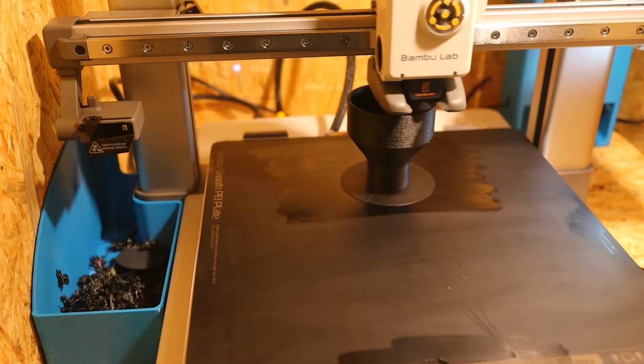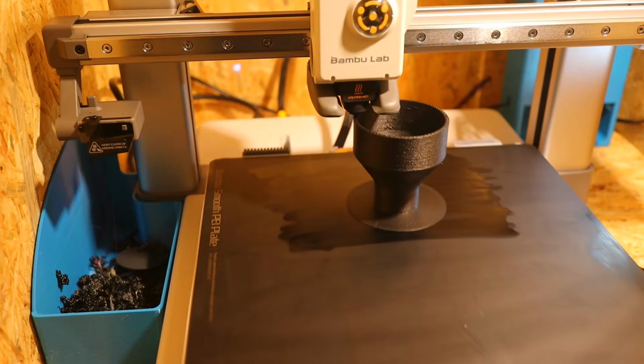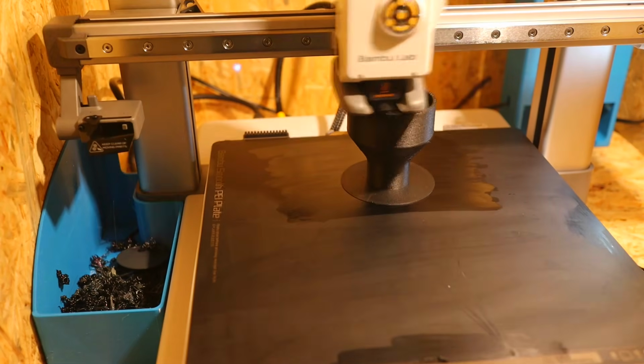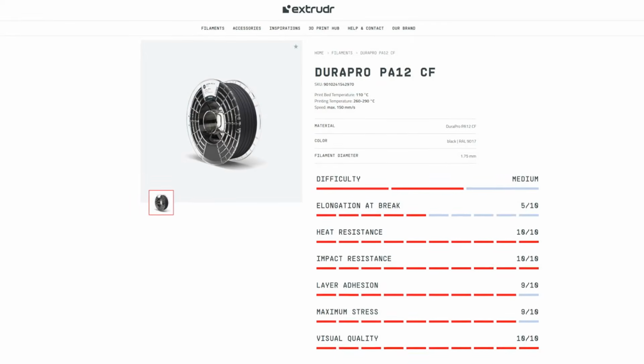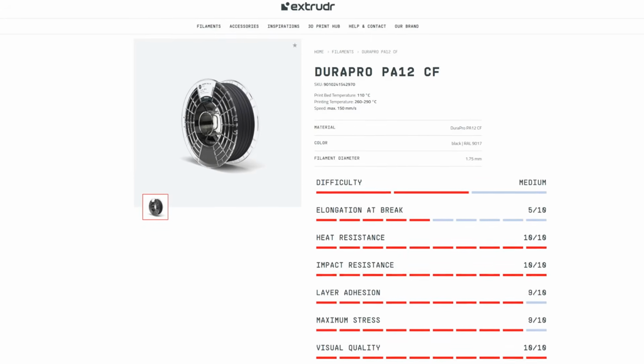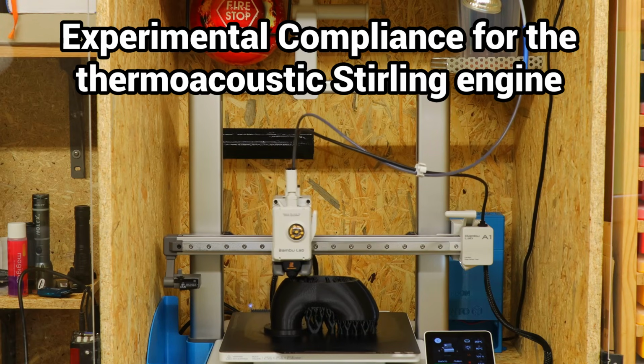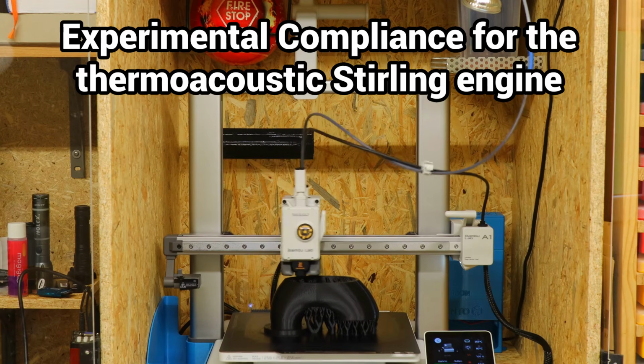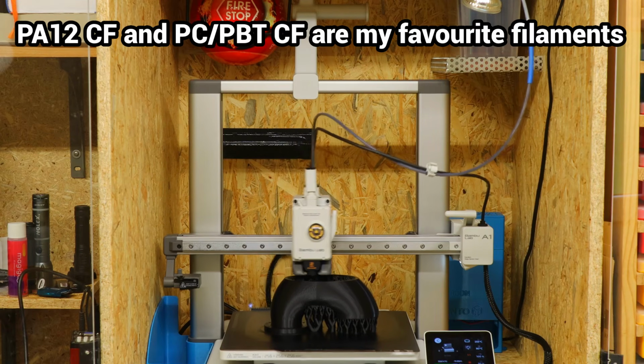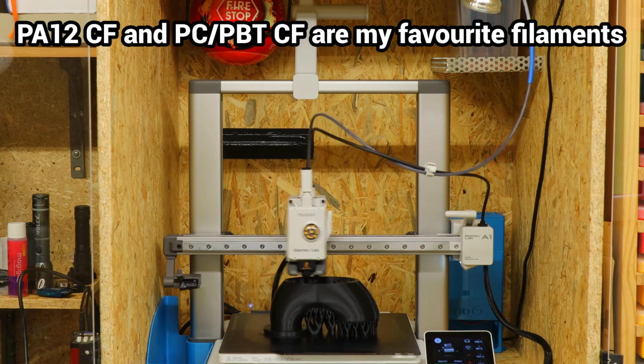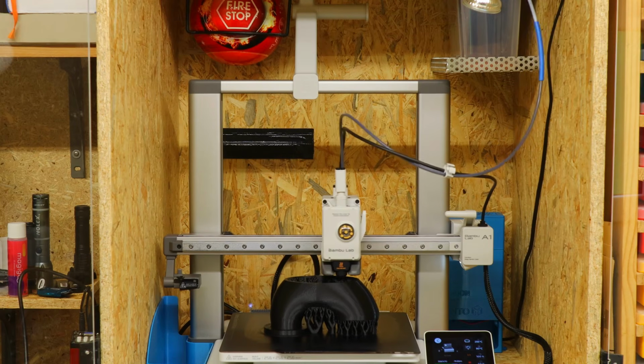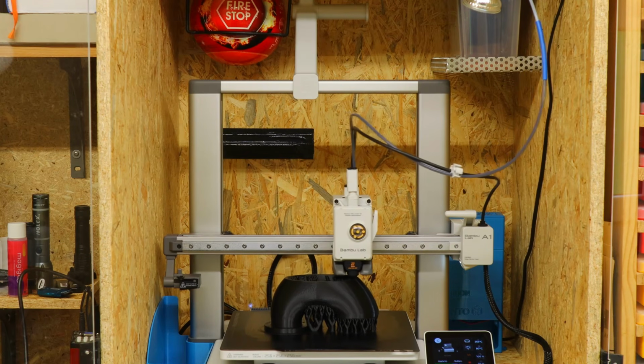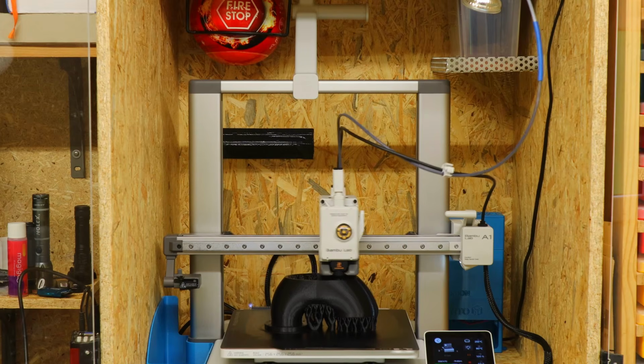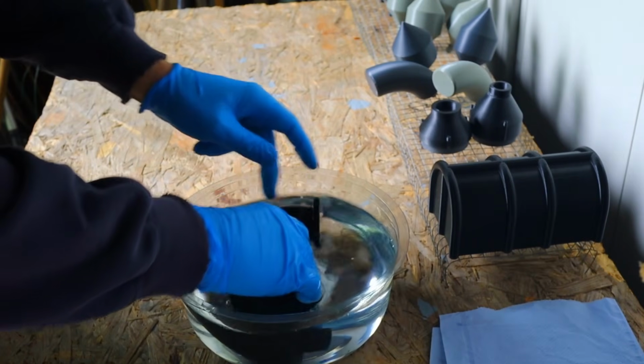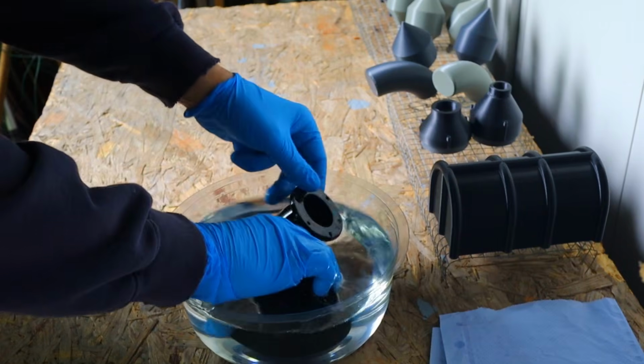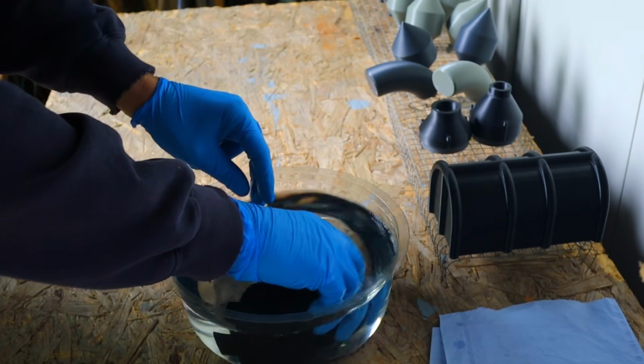Overall, carbon fiber reinforced engineering filaments show higher compressive strength with thinner wall thicknesses, which is probably mainly due to better layer adhesion. So, I will probably manufacture my high-pressure components for the thermoacoustic Stirling engine from carbon fiber reinforced PA12 or PCPBT. These materials have made the best impression for me and achieved the best results in the pressure tests. Many have reported problems with water absorption and brittleness in the long-term usage of untreated PA printed parts.